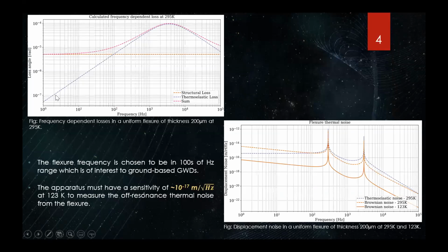So what you see over here on the top plot is the loss for a flexure that I've shown earlier. It's a 200 micron thick flexure, and at room temperature, this is the kind of loss we expect to see, where the pink dashed line is your total loss from structural and thermoelastic loss. And if you convert that into a displacement noise on your y-axis versus frequency graph, then this is what it looks like. The dashed lines indicate room temperature models for the thermoelastic and Brownian noise, whereas the solid line is a preliminary estimate of what it would look like if we were to cool the flexure. As you can see over here, the sensitivity we're trying to measure is 10⁻¹⁷ meters per root hertz, which is really small. So it requires a large amount of isolation to make measurements for this.